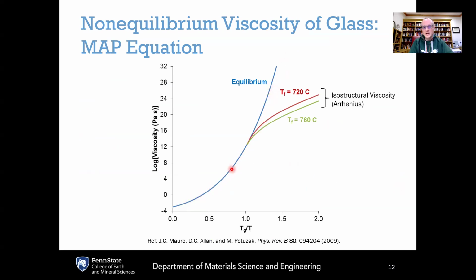As was noted by Prabhat Gupta in that second paper, what happens is when you get to viscosities at or a little bit above 10 to the 12 Pascal seconds, we have this falling out of equilibrium. Now, in that paper by Zanotto and Gupta, they had considered the theory at the time was kind of a sudden transition from equilibrium to this isostructural viscosity that has this Arrhenius scaling. Since then, a new equation had been developed, this MAP equation from these authors here shown at the bottom. And the MAP equation provides a more accurate description of this glass transition process, where it's not a sudden transition from the liquid to the glassy state, but rather a gradual transition.